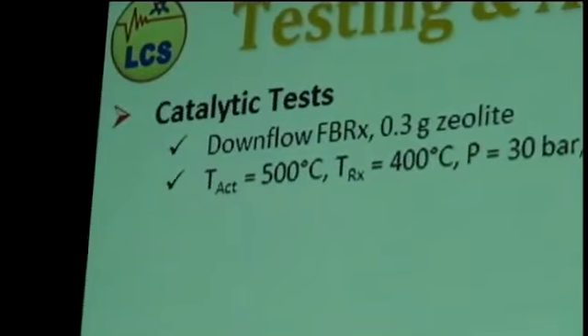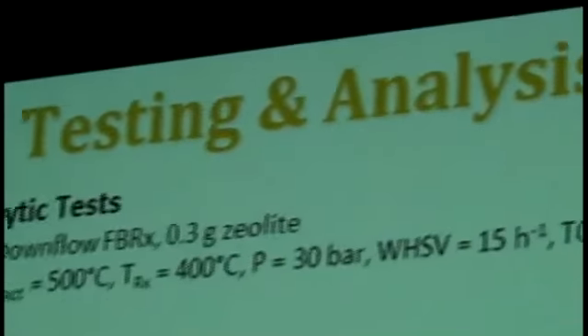The test is with the starting material ethanol that we want to transform into hydrocarbons. What we want is, we don't want to do a kinetic study, we just want to load the catalyst with coke, and then we want to remove the coke. So we have chosen a relatively severe condition after an activation at 500. Reaction takes place at 400, 30 bar under these conditions, and the time on stream is between the initial conditions and about 150, 160 hours.